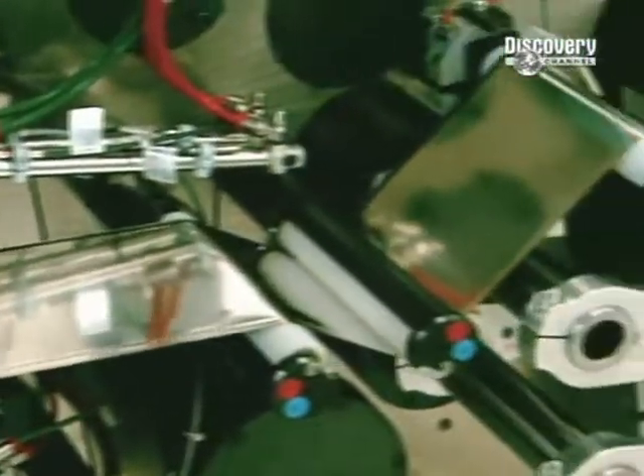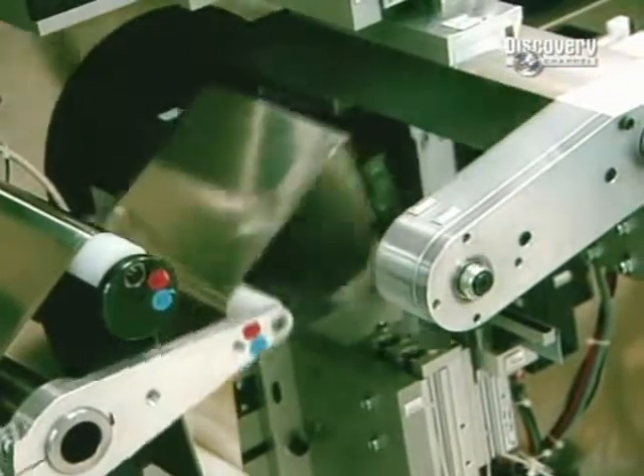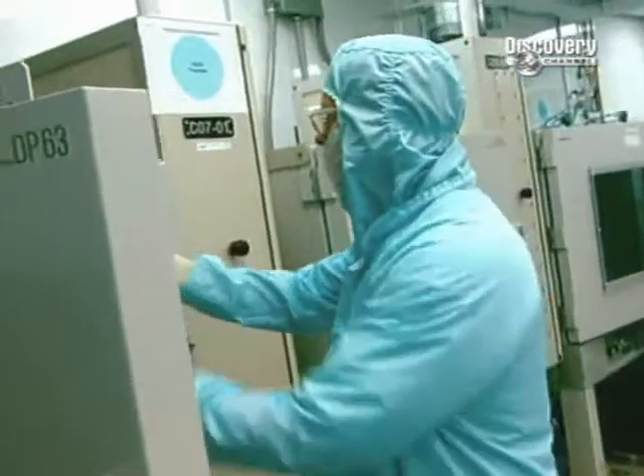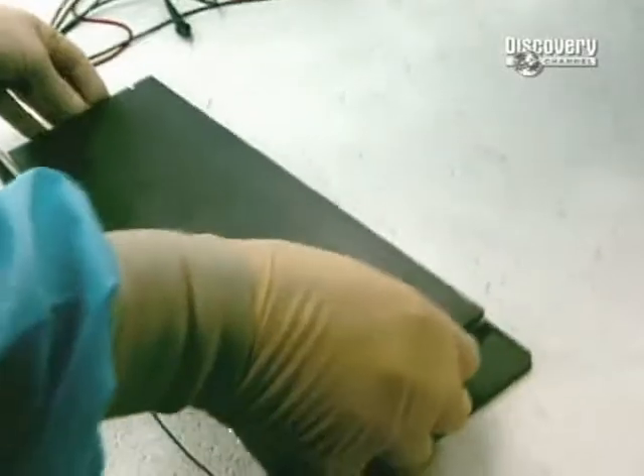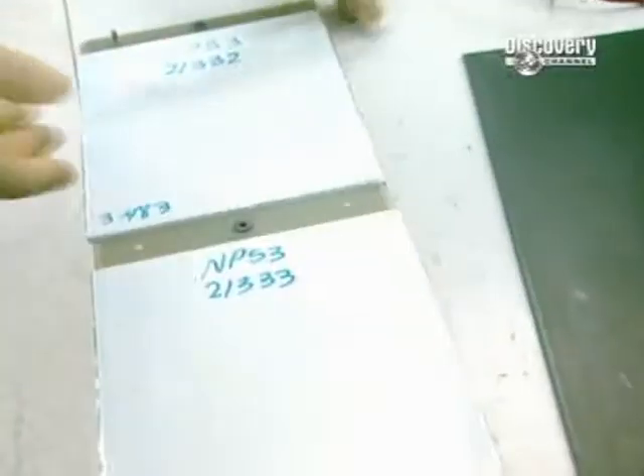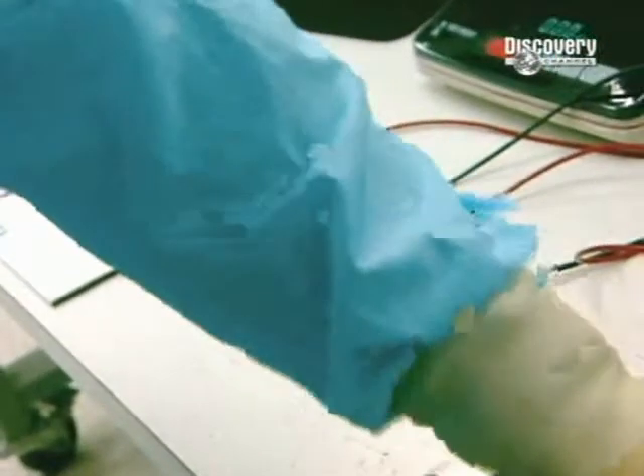The sheet will be used to make individual battery cells. These cells will then be assembled in series and inserted into battery modules. To make an individual battery cell, the sheet has to be rolled up. This automated spooling machine winds up the lithium film in 26 revolutions. The wound-up sheet is put into a vacuum oven, where the various layers adhere firmly to one another. This step lasts for about 90 minutes at 80 degrees centigrade.